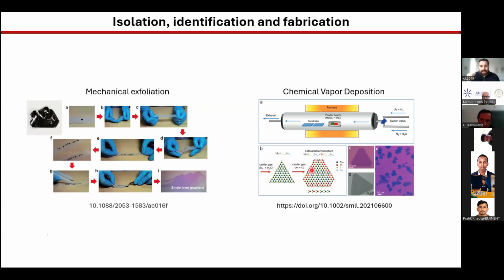There are other ways, like liquid phase exfoliation: you just get your crystal, you place it in a solution or in a solvent, and with sonication, you break away the crystal, and you might end up with a dispersion of monolayers. But in this case, the monolayers that you will get are very small and they're not very easily manipulated. Now, let's assume that we stick to the mechanical exfoliation technique.